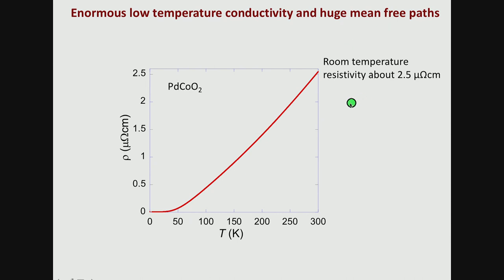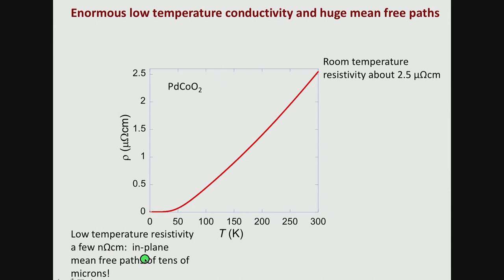The next good point is that the room temperature resistivity is extremely low because the conductivity is extremely high. But as you go further down in temperature, the resistivity falls even further, such that you can do a low temperature resistivity measurement and deduce that the mean free path for motion in the planes is about 20 to 50 microns. It's absolutely huge. In the semiconductor business, it took 30 years of refinement and special growth techniques to get to mean free paths that long. In these materials, they're jumping out at you when you do a very simple crystal growth, sometimes using a vapor, sometimes using a liquid.